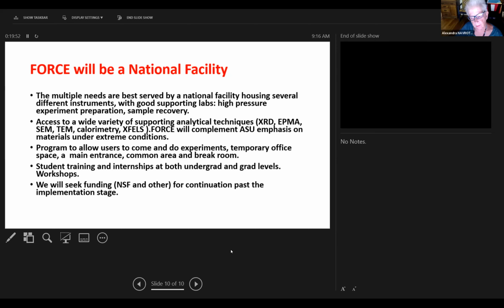So then let me talk about some of the things that FORCE can do that might be of interest in terms of our current projects, in terms of MotU, and of course, in terms of PIRE. One of the things we do not know in any detail is how polymer-derived ceramics and fibers and so on respond to pressure. We know that for normal silica, one has phase transitions in the solid state, the quartz to coesite to stishovite, and stishovite is the rutile structure, so we get octahedral silicon in that structure. We know that silica glass can be densified at pressure.